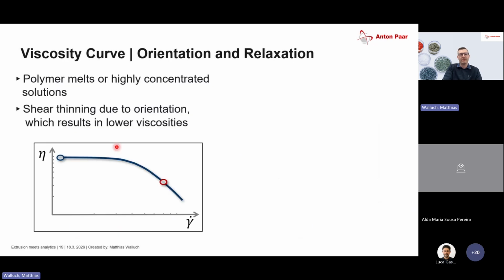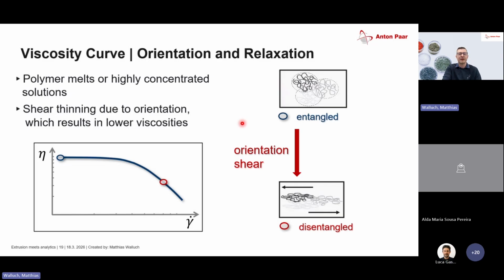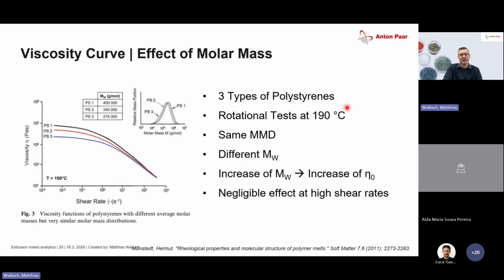So if we want to compare this with a measurement, we see here a standard viscosity curve with a shear plateau in the beginning at low shear rates, and we increase the shear rate, and we see at a certain point the viscosity starts to decrease. So what's happening here? In the beginning, at the blue spot, we're entangled, like we have seen on the slide before. Then we start to move and move and move and do some orientation. And when we are at the red spot, the material looks like this here. So we have shear orientation. And now if we just let the material go again, so we just take the force away, the material tries to get back. Like entropy, over time it's going back to its relaxed state. So this is what's basically happening during viscosity measurement.